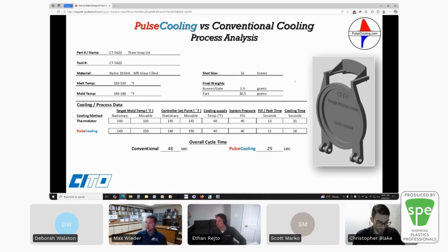Being that we do not use conventional cooling in our molding process, we decided to run the process both ways to show real-time results. As Chris mentioned earlier, we're coming in with a 40-degree cooling supply and a 40 psi system pressure. We recommend a 40-degree delta T and 40 psi system pressure to achieve optimum results.